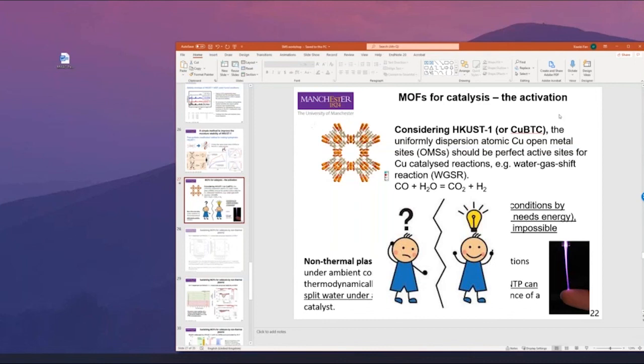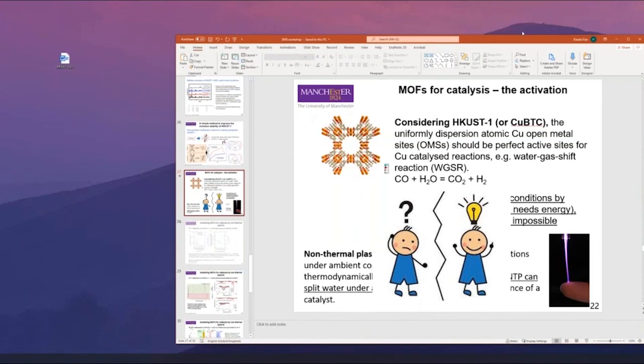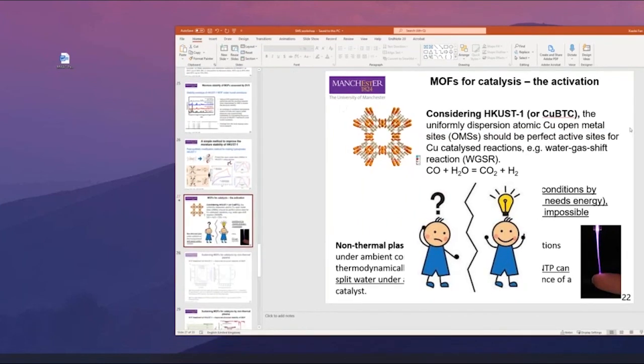Thank you. We have a question here. Have you tried these tests with metals other than copper? Other groups, basically. We tried this one first, and then the student who conducted this work went to our chemistry group, and we have a MOFs group over there. They have done further work in this area. The combination we developed here is actually generic. My group didn't follow up this direction because, as I said, I'm not an expert in MOFs. But there are two other groups using other MOFs based on other metals for different catalysis, because they have developed MOFs with selective absorption of NOx. Combining plasma activation, they show that NOx conversion is also possible with the combination of MOFs plus non-thermal plasma.